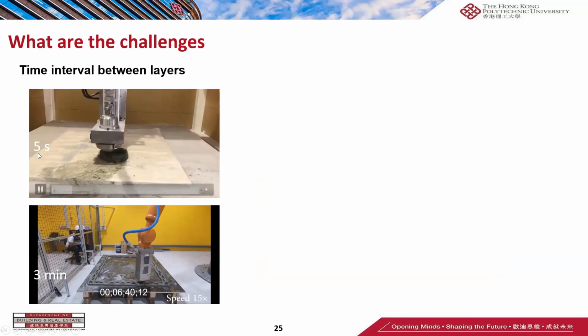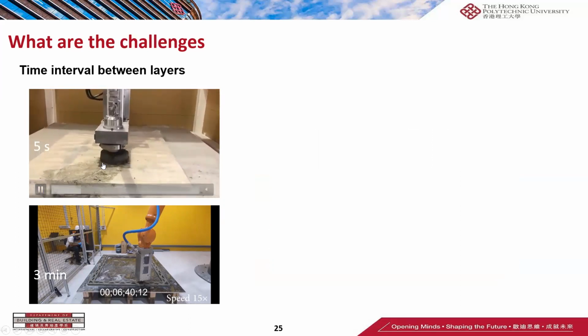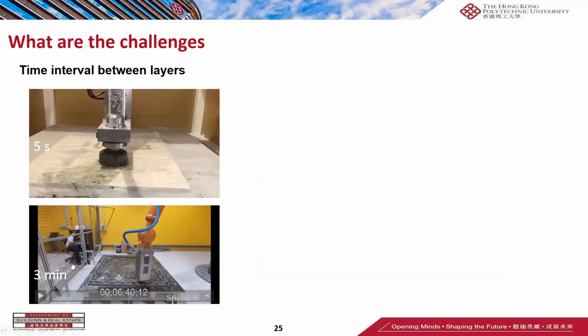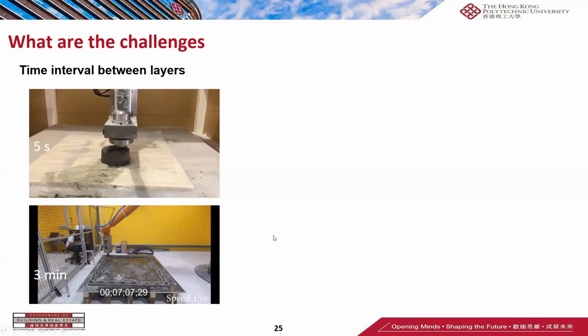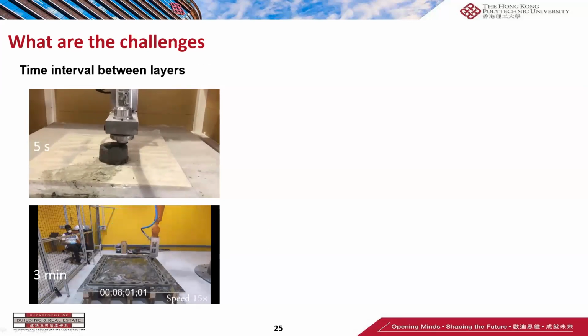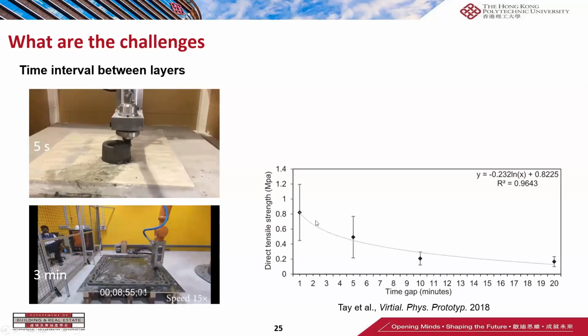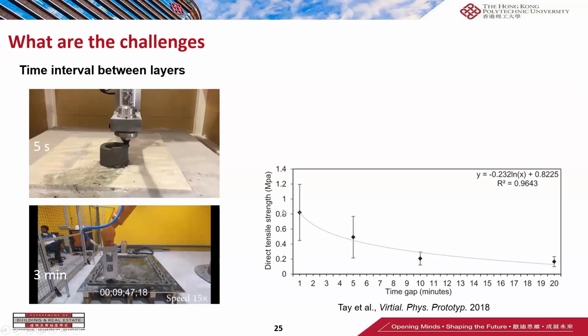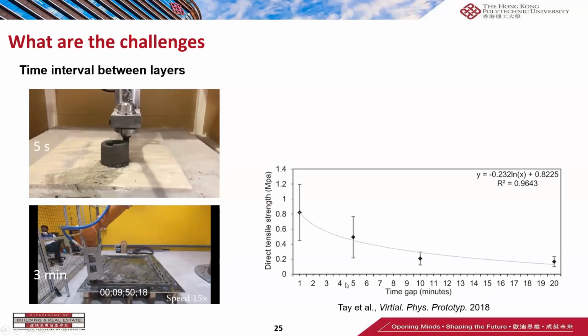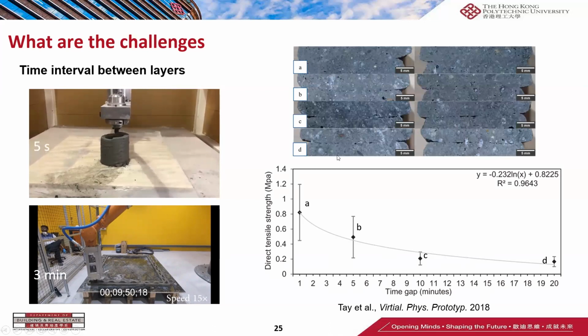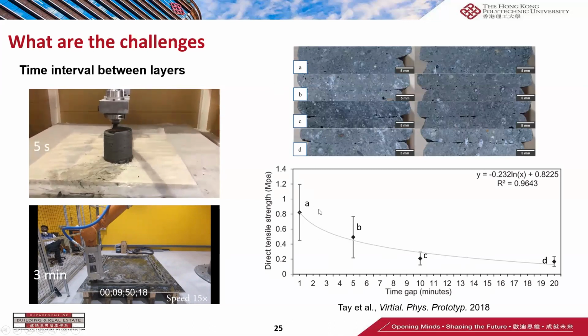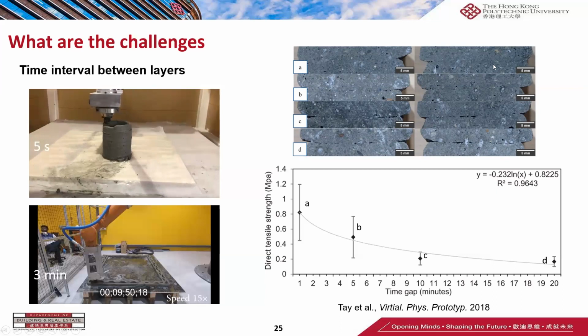For a small structure, maybe the time is quite short, maybe several seconds, that we can finish one layer of printing. But if we print certain large structures, just like this, the time interval between layers can be as long as several minutes. With the increase of time interval between layers, it will affect the mechanical performance of the interface, just like this. You can find that with increase of time interval, the mechanical performance, especially the direct tensile strength, will decrease. Apart from the mechanical performance, also the porosity of the interface, just like this, with increase of the time interval, the porosity of the interface also increases. So that's why the interface is a big challenge in this area.